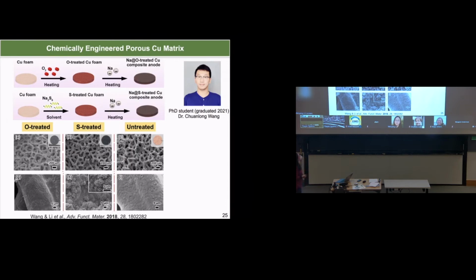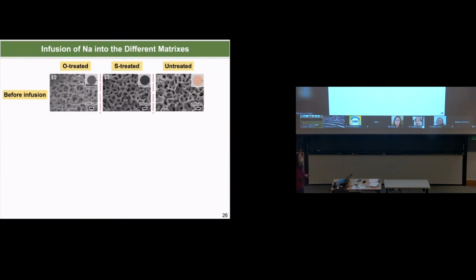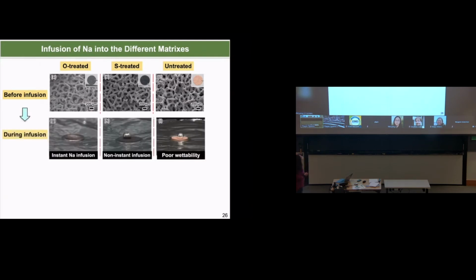Then we compare the surface structure of all these different surface-treated copper foams. This is an untreated case. This is the sulfur-treated case, where the surface has a flaky-like structure. This is the oxygen-treated one. Why we are doing this is because we are trying to infuse sodium metal into different matrices. Especially for the oxygen-treated case, if we melt the sodium, because as I mentioned sodium has a very low melting point, we can easily infuse sodium metal into the oxygen-treated copper foam. It can be instant, we call it instant sodium infusion.